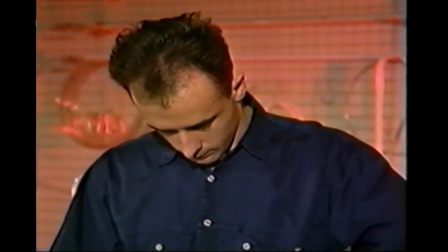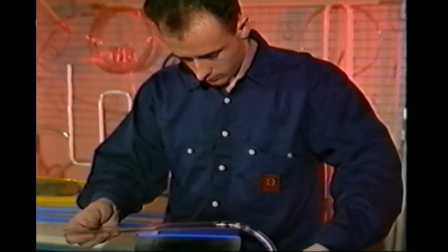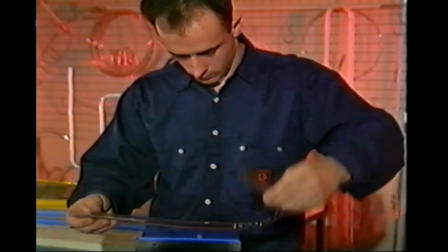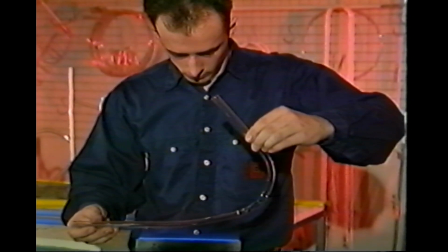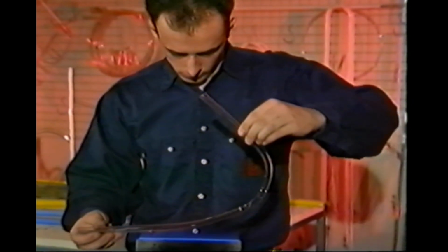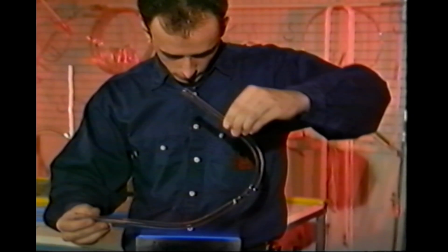Before showing the outside radius extra melt, it's easier to explain how the second side must be shaped to create the correct shaped curve. When the tube is hot, it will bend easier in area 2. Areas 1 and 3 need to be hotter on the outside so they can be bent in a particular order to create the shape. When overall melting is achieved, cease rotation with the first side curve vertical. Melt the underside slightly at the same time, creating a gentle radius by lifting the ends. Move the curve along the flame so that area 3 melts a little more. Then, without disturbing the shape, move the curve back the other way so that area 1 melts a little more.